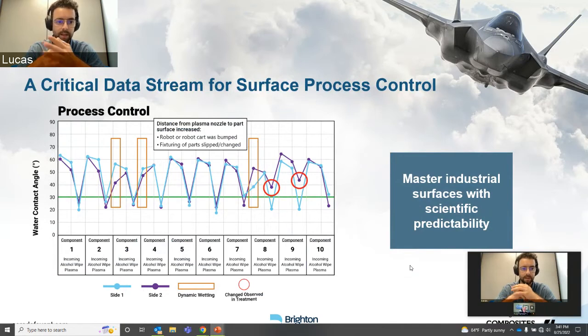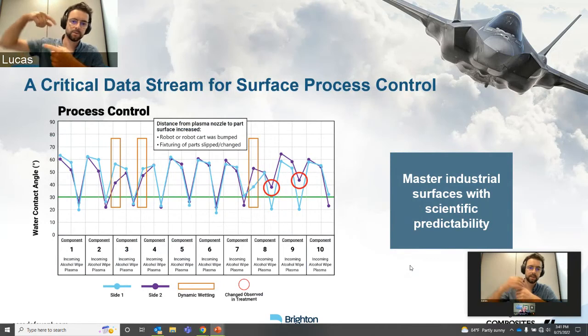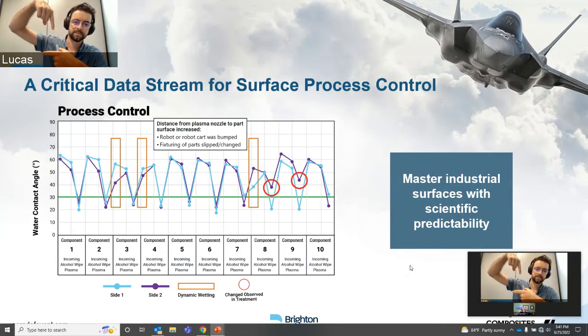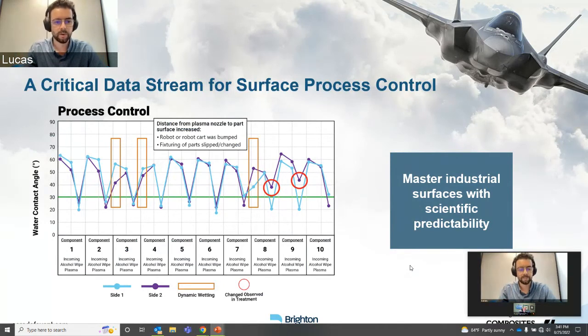Great. If we go to component 8 and 9, though, and you look at the circles around the purple dots, our post-plasma measurements are showing us in the 40s, right? It's like a 39 and a 45. Totally different. What happened? We go and investigate. An operator had selected the wrong robot program, which was moving that plasma jet farther away from the surface. So we were able to flag that before those parts were fully assembled and shipped out to the customer for reliability testing, on your favorite new electric Mercedes or whatever it is you're buying.